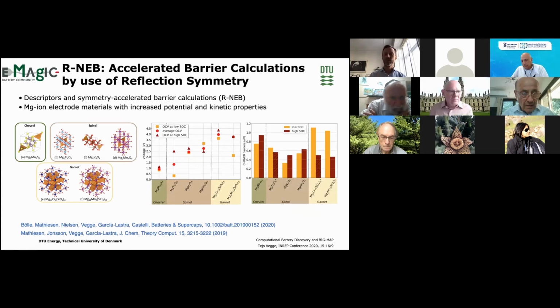So you see here we have candidate materials that actually have kinetic barriers in excess of 1 electron volt, which is also the case almost for the Chevrel phase. So we tried to do it conservatively, because we actually ended up having only a few candidates that had high OCVs at both high and low state of charge, and also interesting kinetic properties. So we try to be conservative when we do this. And I see a second example, and that was actually a slide that I cut.